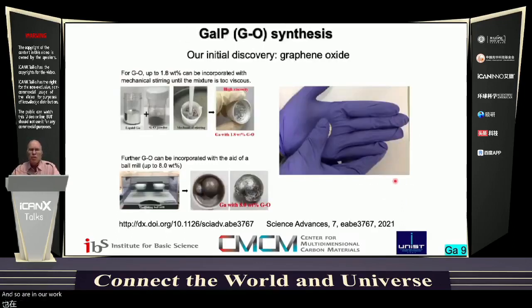In our work, we were following on an accidental discovery where we learned that graphene oxide would be wetted by the gallium. And this was somewhat surprising because it's known that gallium does not wet diamond and does not wet graphite, and it does not really wet a lot of different carbon materials. So we were curious, and I challenged team members such as Dr. Chunhui Wang to see whether he could mix the materials and try to make interesting composites. And at first, Chunhui worked by hand in air in lab environment. Then we went to a mechanical stirrer, or as you can see here, an oscillating ball mill.